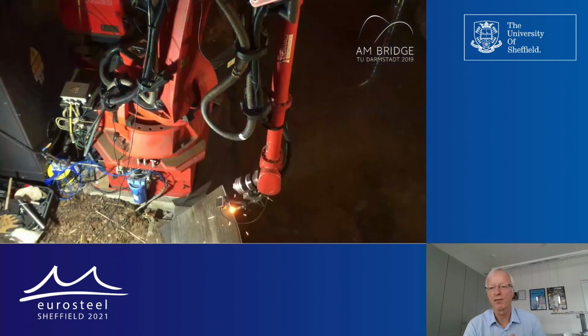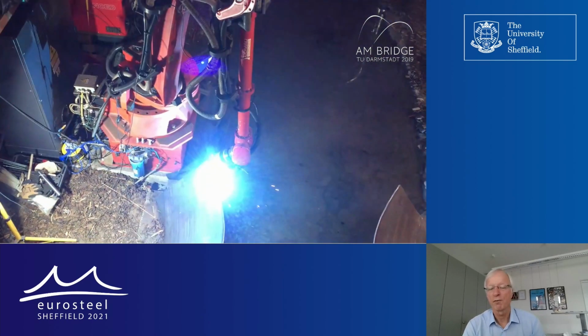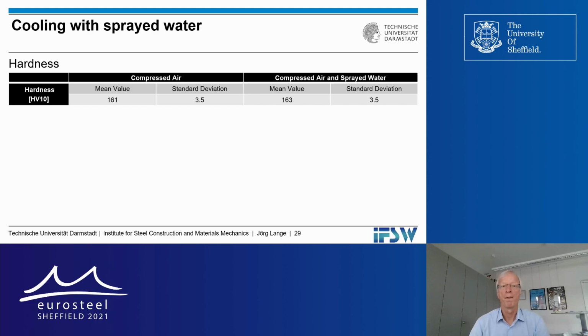We changed printing from the left-hand side to the right-hand side because that gives us some time for cooling. If you print horizontally, it's very important that you have enough cooling time so that the freshly printed drop of steel will cool and not fall down and drop into the water. So we need a very special welding system. This was a CMT welding method. And if you print left-hand side to right-hand side, that takes a little longer because the robot has to move back and forth, but that gives the other side enough time to cool down. So if we put on the next drops, they will cool down also and not drop into the water.